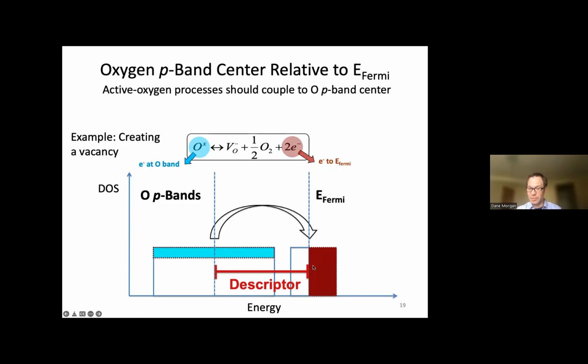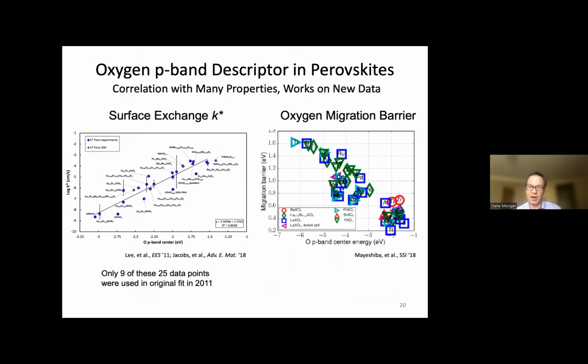So this descriptor, this distance between the P-bands and the Fermi level, should give you a really good qualitative feel for the energy of redox in your system. And that means it's going to capture things like the energetics to form vacancies, or to bind oxygen onto the surface, or other properties that involve exchanging oxygen and moving oxygen around in your system. And that is exactly what we find. So here are a couple of correlations with this oxygen P-band center.